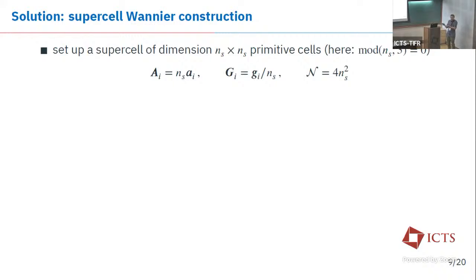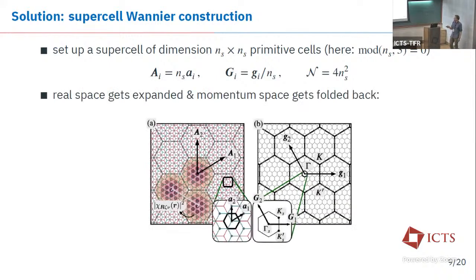So this is one time where using a moire setup is actually beneficial and not overcomplicating things, where we set up an artificial supercell of a certain linear dimension in primitive cells, and treat the model in terms of these supercell lattice vectors and supercell reciprocal lattice vectors that are now rescaled by a factor of 1 over the number of cells, and then look at the non-interacting properties as well as interactions on that supercell. Now, real space gets expanded by a factor of ns, and momentum space gets folded back.